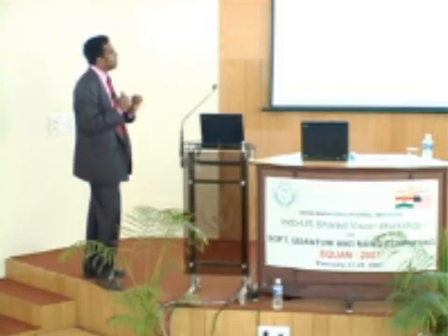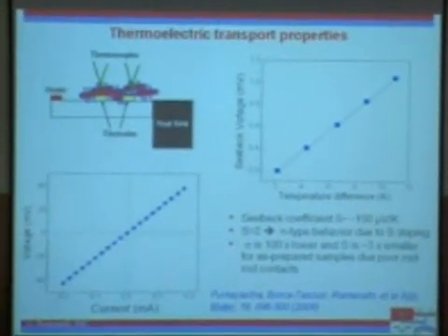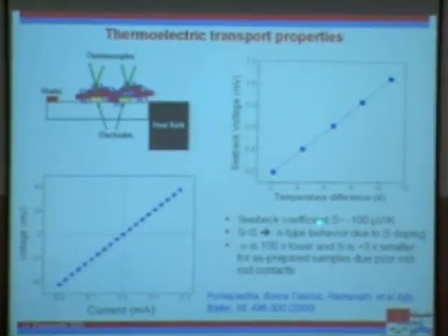And the idea here is, of course, since thermoelectrics, you want to get high electrical conductivity and you want to get low thermal conductivity, right? The electrical conductivity you want to tune by using quantum confinement, so getting more states near the Fermi level, but low thermal conductivity you want to obtain by the size confinement because of the phonon scattering from the surfaces and the boundaries of the structure itself. So the films of nanostructures that we've made give us very promising Seebeck coefficients and also electrical conductivities, which we are hoping, when integrated with the interconnect structures in conventional nanoelectronic devices, could be a way in which you can dissipate heat.